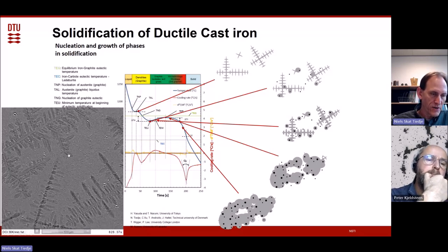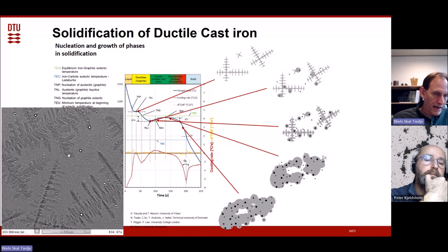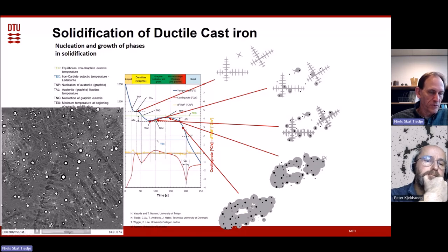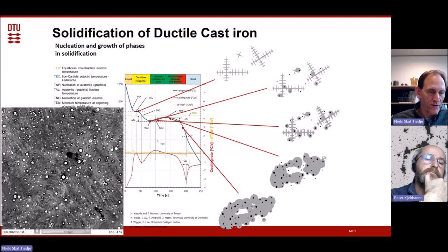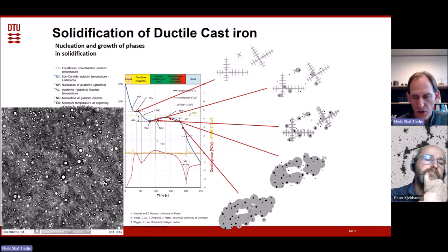And we can see that because the dendrites contain a lot of iron, there will be a lot of carbon in the melt. And of course, the graphite forms in the melt. We also see that graphite is lighter than the liquid, so it floats.